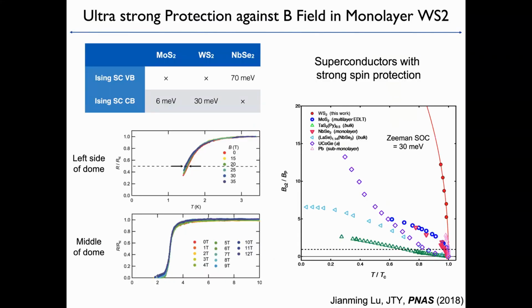So this idea can actually be tested with another system, tungsten disulfide, which is having a larger Ising type spin orbit interaction at the K and K prime points. Previously molybdenum disulfide had 6 meV Zeeman SOC. For tungsten disulfide, we can have 30 meV. And with the 5 times larger protection, we are actually having a much stronger superconducting state against the external field. So now I have a superconductivity with roughly 1.5 Kelvin TC. And if you apply a 35 Tesla B field there, you can hardly change anything for this superconducting transition.